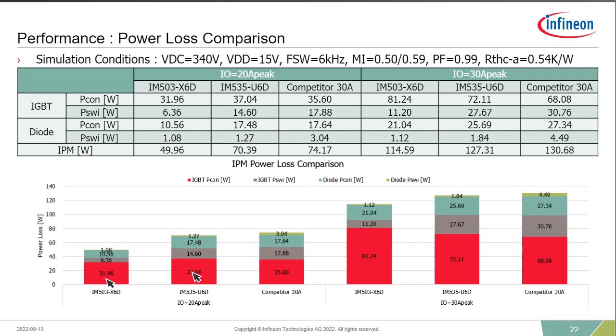And what you see at a 20 amp peak current rating is that your losses are in the range of, for instance, 49 watts for a silicon carbide device, or 70 watts for an IGBT-based device. And one comment here too is this is based on the 15 volt VGS specification. If you were to increase this to 18 volts, you would see a substantial improvement in the RDS-on specification of silicon carbide devices, about a 25% improvement. So your losses, particularly from the conduction loss perspective, would go down by about 25%, and your losses would be in the upper mid 35 range. And then the same calculation is also done here for a 30 amp peak current.